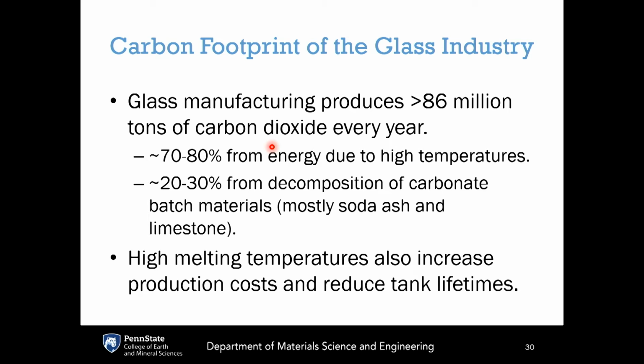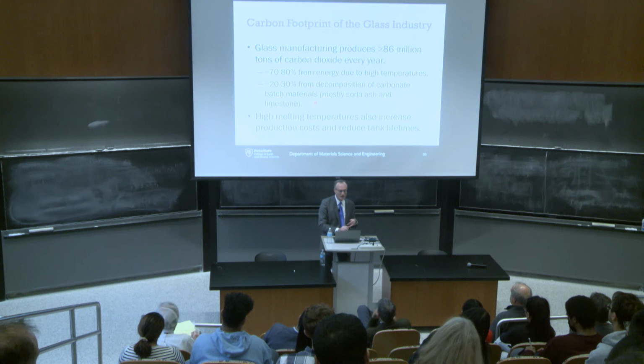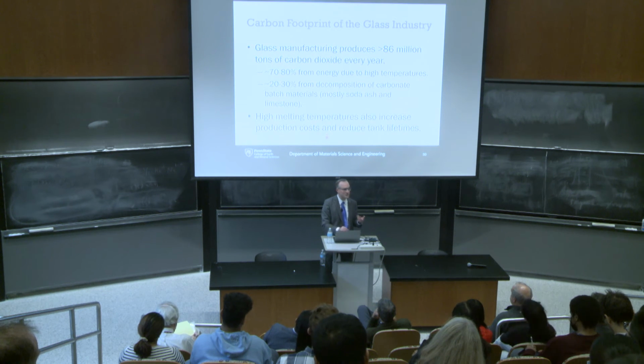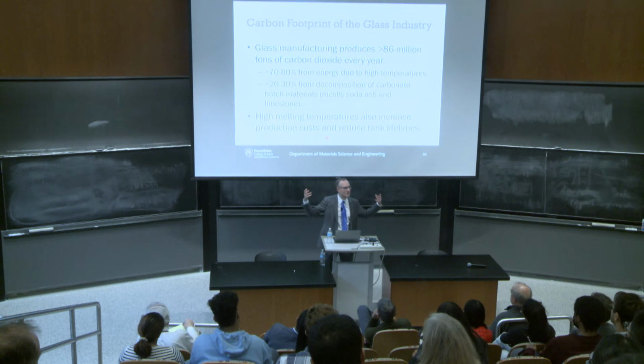Although I focused on high-tech glasses, the fact is that about 95% of glasses being made and sold are the traditional soda-lime silicate glasses that are found in your windows, the glasses that you drink out of, and so on. So most of this comes from energy consumption, but about 20 to 30% of this comes from the decomposition of carbonate batch materials. So we call it soda-lime silicate glass because 2 of the raw materials are soda ash, which is sodium carbonate, that decomposes into sodium oxide and releases carbon dioxide, and limestone, which is calcium carbonate, which also releases carbon dioxide during the melting process.